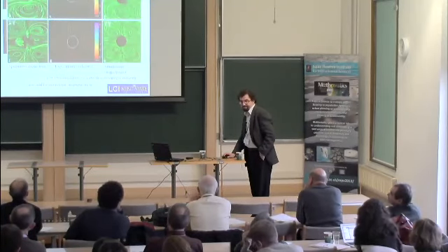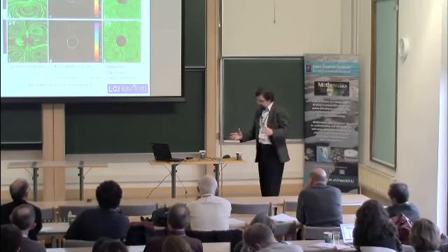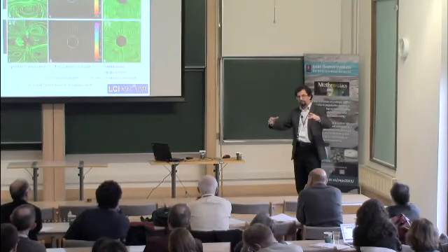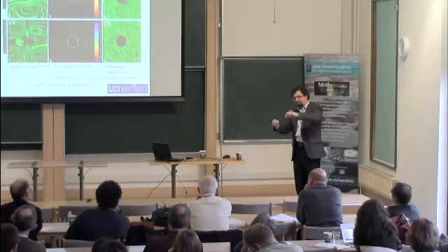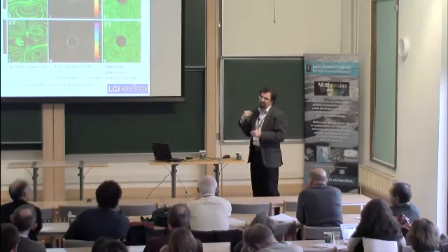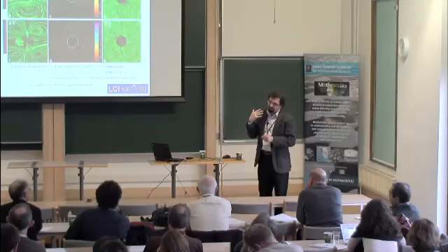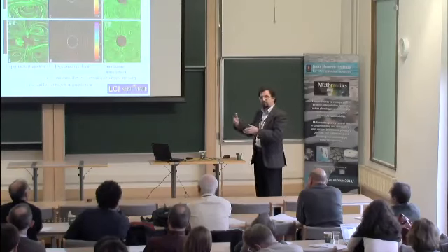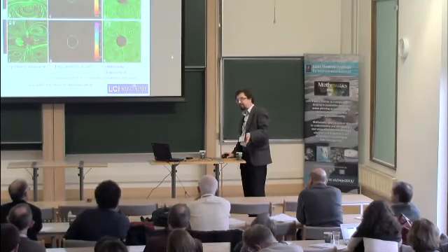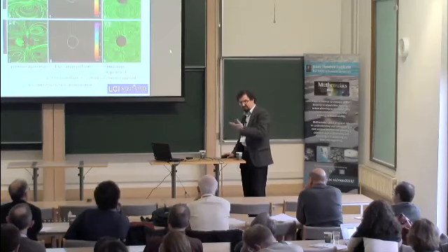How do you measure those trajectories? We just apply an electric field and then make zillions of photographs, and then there is a special technique that allows us to connect the images. You actually see the charges? No, we see the motion of fluid through the fluorescent dye that is added, but then we change the concentration of ions.